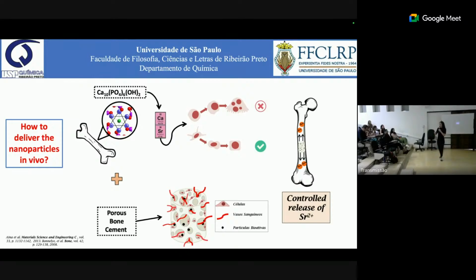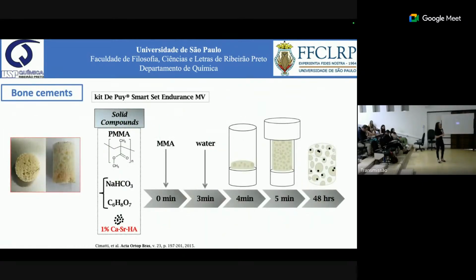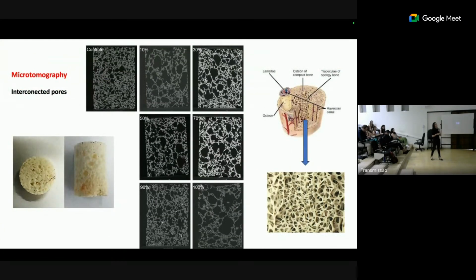Another way to deliver these particles is incorporating them in bone cements. So we prepared here some PMMA bone cements. We added the nanoparticles, and we implanted these bone cements containing the strontium phosphate nanoparticles in the femurs of rabbits, the tibias of rabbits. So the structure of these bone cements, here it's better, shares similarities with the structure of trabecular bone.